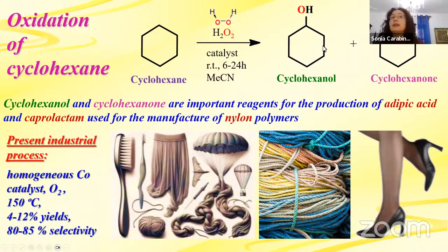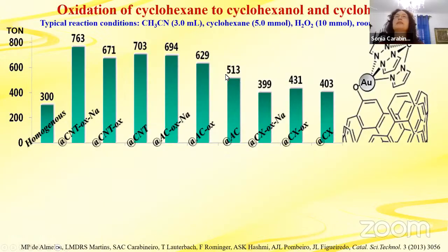So the industrial process for this reaction uses a homogeneous cobalt catalyst, oxygen, 150 degrees, and it only has 80 to 85% selectivity, and the yields are very low, from 4 to 12%, in the current industrial process. So if we can improve this, it's very good. And we could, using hydrogen peroxide at room temperature, and as we are going to see, only 6 hours of reaction, so it was better.